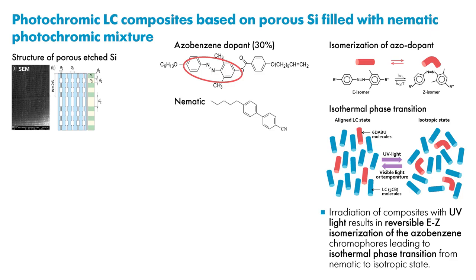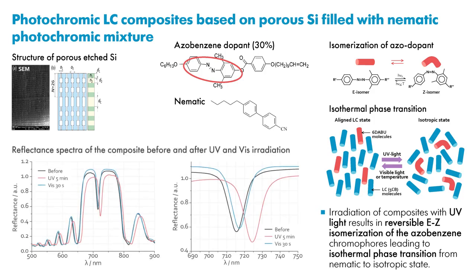Due to the presence of lateral methyl substituents in the azobenzene chromophores, the photoinduced Z isomer possesses very high thermal stability. Back transition from isotropic phase to nematic one takes place for about 40 days at room temperature. This makes the prepared photochromic mixture very convenient from the point of view of investigations and practical applications.